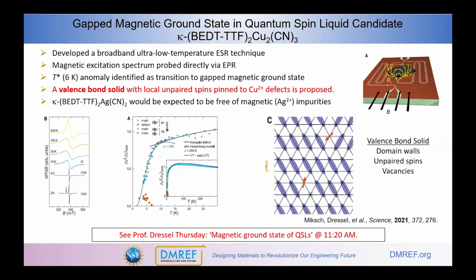But in recognition of the work that was done by Martin Dressel's group, somewhat more recently, he developed this broadband ultra low temperature ESR technique to be able to study these magnetic excitations directly from EPR. This anomaly that had been identified at 6 Kelvin for many years was identified as a transition to a gapped magnetic state or a valence bond solid, with these unpaired spins pinned to copper-2 defects. There are copper-2 defects in these materials partially because during the electrocrystallization process, you are doing an oxidation of a copper-1 system. So some copper-2 will probably inevitably work its way into the crystals.